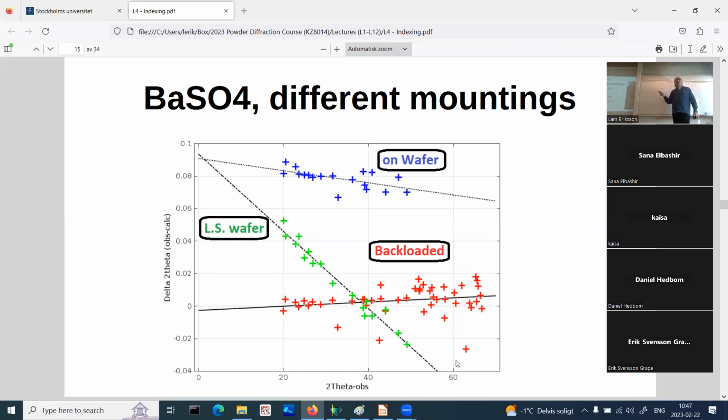So why doesn't it scatter? It's because it's cut in a direction where there is no reflection, at least within the copper sphere. But if you put this into silver radiation, for example, with 0.5 angstrom wavelength, then you go that far out in reciprocal space and it does scatter. Unless you have silver, you won't recognize it. And with copper radiation, it's very, very silent.